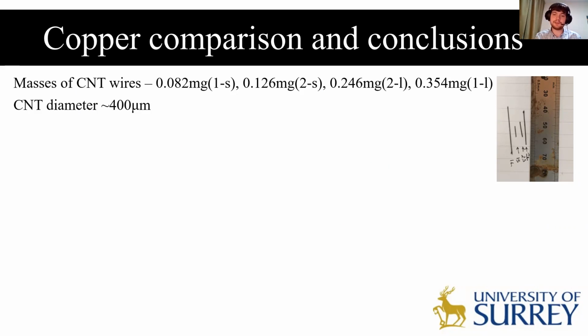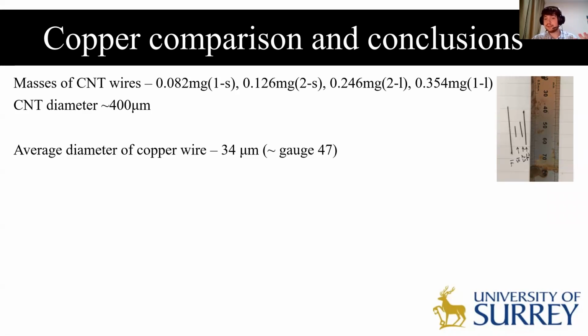Since it was previously shown that decreasing the diameter of a carbon nanotube does not make them less conductive, it's better to use the mass of the carbon nanotubes as a comparison to copper. The masses of the carbon nanotubes have been recorded, and the diameter used for the calculation was 400 micrometers. If the mass as well as the length of the wire is taken as a constant, we can use the density of the copper to work out its diameter, which would happen to be around 34 micrometers, around 10 times smaller than the carbon nanotube wires. This would also give us a gauge of 47.